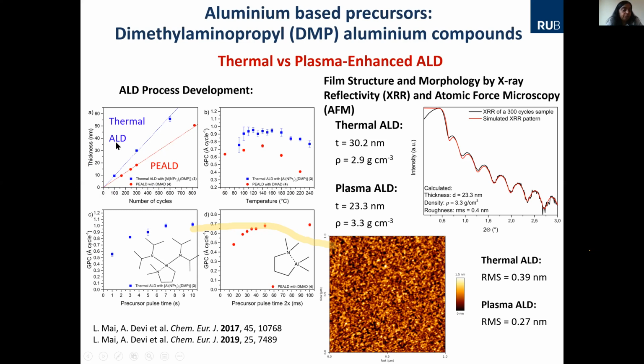And here you can see, maybe you can recall the first slide where I showed the linearity, that means the thickness as a function of number of pulses, or also you can see there's the ALD window where you have a broad range where you can operate as a function of temperature. So you measure the thickness or the growth per cycle as a function of temperature, and then also the saturation. After some eight pulses of a precursor, the growth saturates. Then you introduce a new precursor, and then it continues. So we can also change the precursor pulse, the water pulse. These parameters can be varied, and then you get a film. And from the X-ray reflectivity, from the fringes here, you can calculate the thickness.